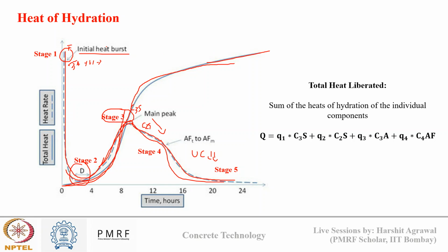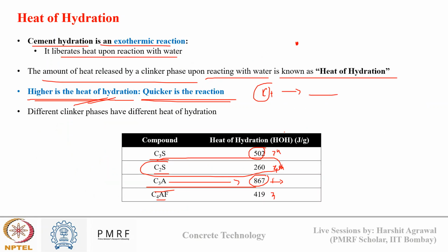Now, knowing the clinker composition, we know how much C3S is there, how much C2S is there, how much C4AF is there, how much C3A is there. We can calculate the total heat of hydration. How? If we know this proportion and we know how much heat of hydration a certain phase requires per gram of that proportion, we can calculate the heat of hydration.